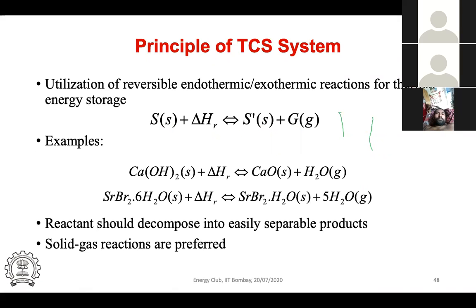and 1H2O will remain. At a higher temperature, not very high, say 80 or 90 degrees, if you heat up again, then that one molecule also goes out of the system. Now again, if you add moisture to this SrBr2, you will recover the 6H2O. Now how many times you can do this is also a great research question.